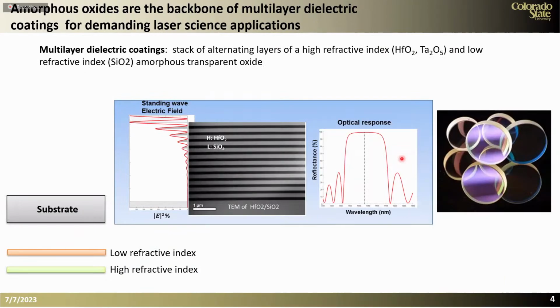So our application of amorphous oxides is in developing multi-layer dielectric coatings. These coatings are essentially a stack in which we combine two materials that have contrasting refractive index. I show here a transmission electron microscope image of a hafnium oxide silicon dioxide multilayer. By selecting the materials and their thickness, we can tailor their optical response. And by changing the relative thickness of the layers, we can also shape the standing wave electric field inside the coating. So this is how we make the coatings, sputtering layer by layer by layer.